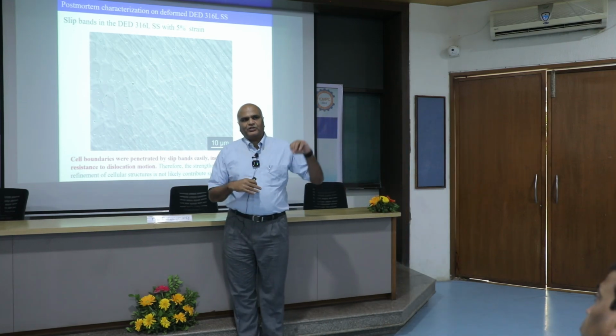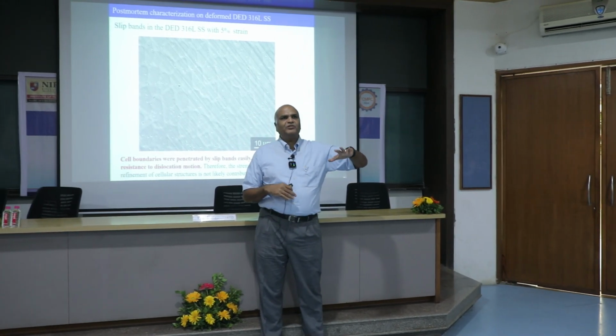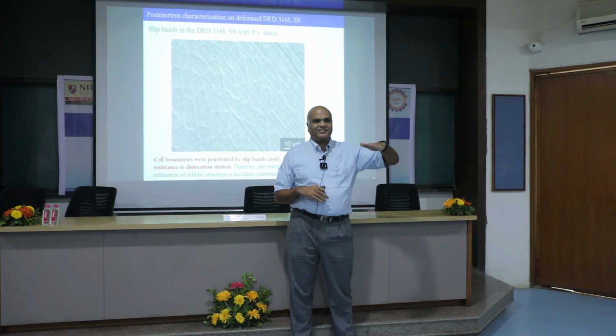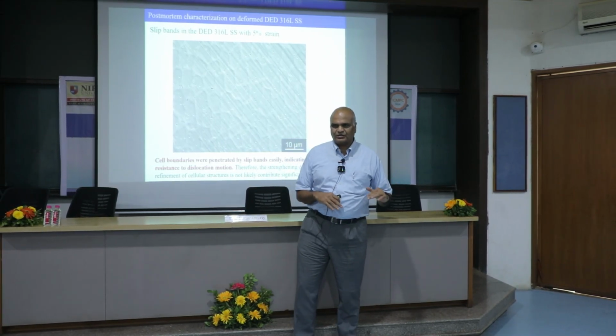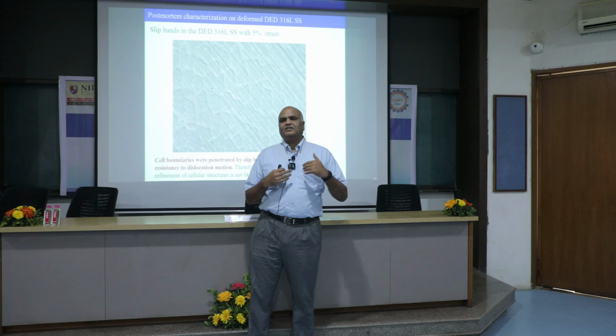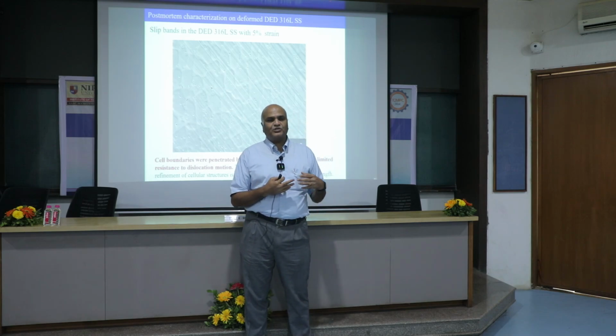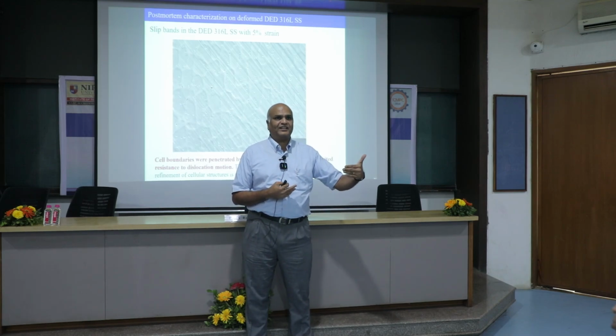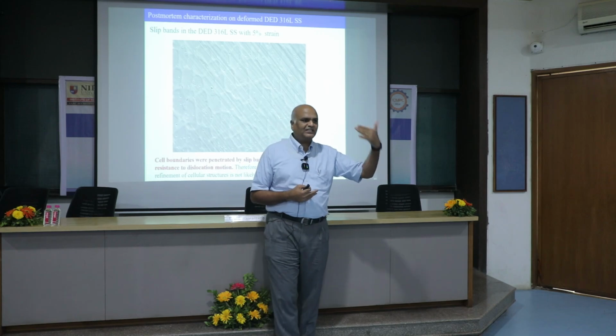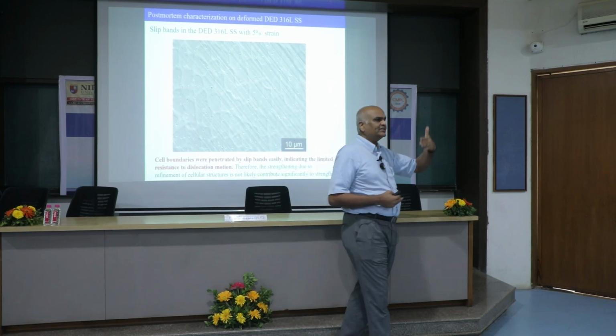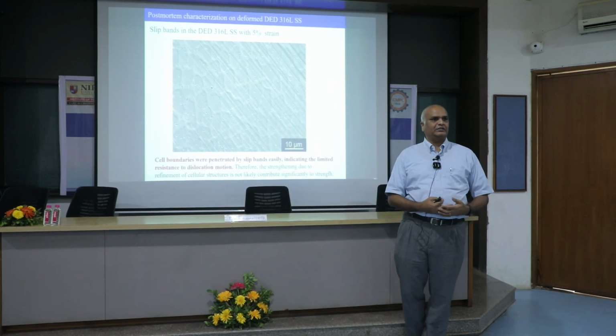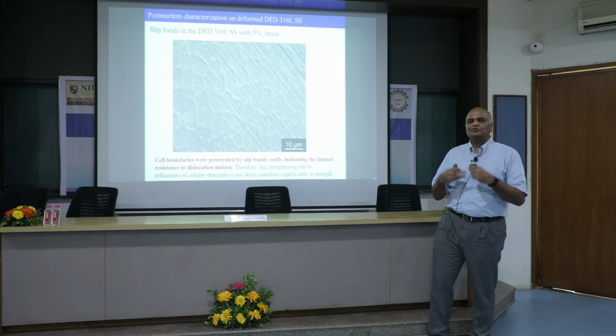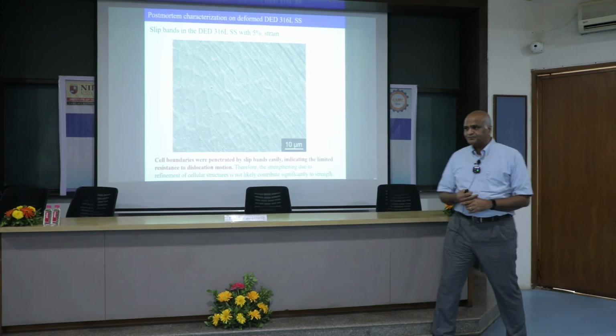Let me go back a step. If you study grain boundary strengthening, the Hall-Petch relationship, everybody, mechanical engineers also, learn about it. What happens is the grain boundaries, high angle grain boundaries, act as red traffic lights for dislocations. When dislocations come to a grain boundary, they get arrested. They can't move anymore. That is the reason smaller grain size gives you higher strength.